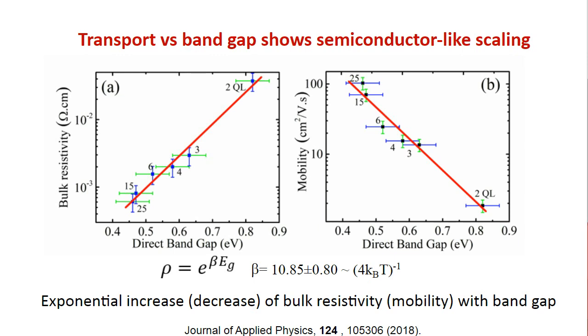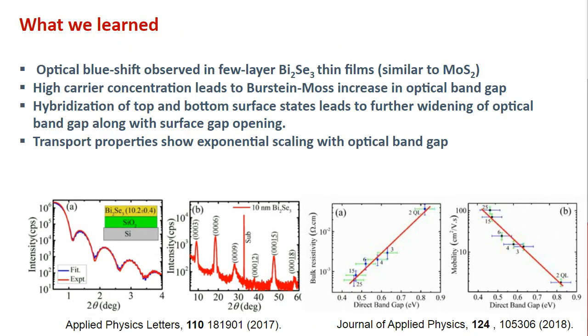So what we learned here is that we observe a strong optical blue shift in bismuth selenide. This is similar to MoS2 actually. This comes back to the question of how the band gap changes when you reduce the thickness. We came back to the same idea for bismuth selenide, even though bismuth selenide is not usually seen as that kind of material. Topological insulators have their own exotic properties that people are after. But we found a simple, semiconductor-like result, like a TMD result here. Again, we are seeing the realization of two effects, the Burstein-Moss and the finite-size effect, which lead to the increase in the band gap of the material. And our results seem to be verified using transport measurements also.